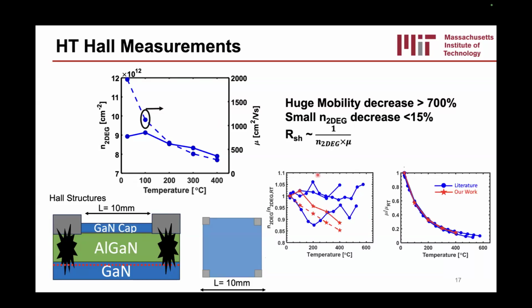And this is kind of in line with other works. Once again, there's not a whole lot of other works at higher temperatures, but the few that there are, about 3, are shown here in blue. And you can see the 2DEG density normalized to the room temperature 2DEG density generally doesn't change more than about 15% plus or minus across the full temperature range up to 500 Celsius. On the other hand, the mobility in our work and the other works in the literature degrades significantly, and it goes from 1 to about 0.1, or 10x, at 500 C.